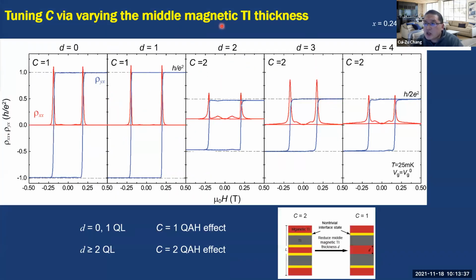In addition to the magnetic doping level, we also tune the Chern numbers by tuning the thickness. Tuning the thickness tunes the interactions between the quantum anomalous Hall layers. And we found that when D equals 0 and 1 quintuple layer, it is a C equals 1 quantum anomalous Hall insulator. When D is from 2 to 4, it is a C equals 2 quantum anomalous Hall insulator.